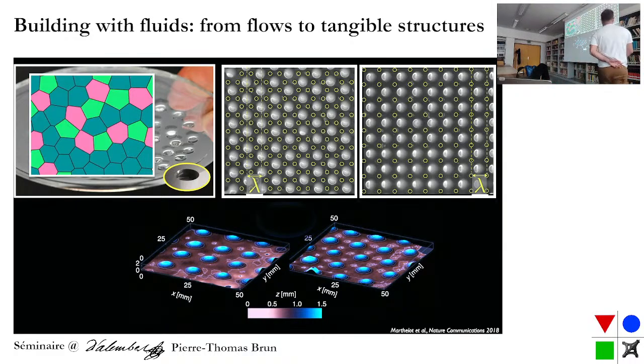Okay, but what I just talked about before is nice, but it's also a bit of a fail, right? Because we were talking about making instabilities for materials, and now we have scales that are about a few millimeters. So this is big. For anyone doing material science, they see millimeters, they're just freaking out, right? So how do we make things smaller? Well, I said that the distance between drops was basically driven by the capillary length, right? And the capillary length is the square root of surface tension divided by density times gravity, right? So surface tension, especially under a square root, you cannot change too much. Density, it's already 1,000 to 1, so it's as good as it gets. And the only thing we can change is the acceleration, not gravity, but we can try to find